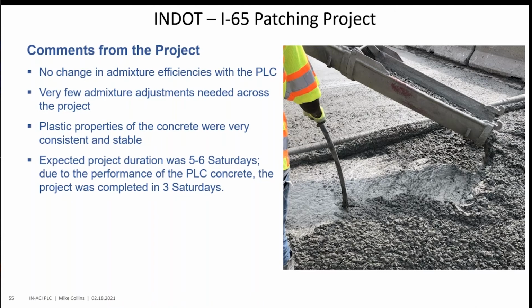I love that picture. You get a good idea of just what kind of creaminess comes to the top there when that concrete's vibrated. And again, some of the comments from that project: no change in admixture efficiencies with the PLC. That's huge. Again, they just pulled one powder out of a typical patching mix, put in the PLC, did have to make a very minor adjustment initially in air content. Once they got that in spec, they just ran with that dosage the entire project. Plastic properties of the concrete, very consistent, very stable. And again, just because of the performance, they were able to cut down on the length of the project.